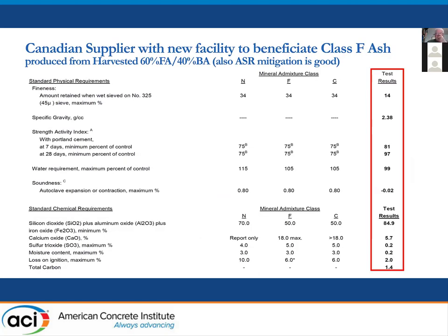Now, as a result of the change that was allowed this year, one of the Canadian plants has already set up a facility to beneficiate ash, which is actually a 60% fly ash, 40% bottom ash blend. They've done ASR testing. They've got sulfate testing in progress, but this is a standard sort of C618 report on it. And it shows that they've got very fine material, with only 14% retained on 45 micron or 325. The strength activity is good at both 7 and 28 days.